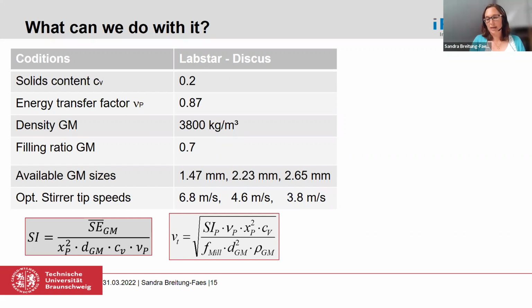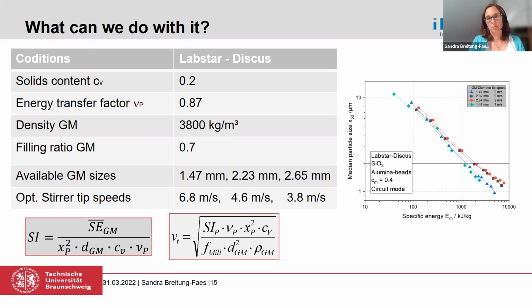And then we looked at the grinding experiments, and this was the result. So at least we have here a typical plot, the median particle size over the specific energy. And we ran the experiments usually with 9 meters per second. So you see here the different grinding media types for 9 meters per second, where at least the smallest ones were already the best. And then we said, okay, we run one with an even smaller stirrer tip speed, and we see that the curve is just shifting a little bit, but at least it's pretty clear the smallest grinding beads are here the most efficient ones.